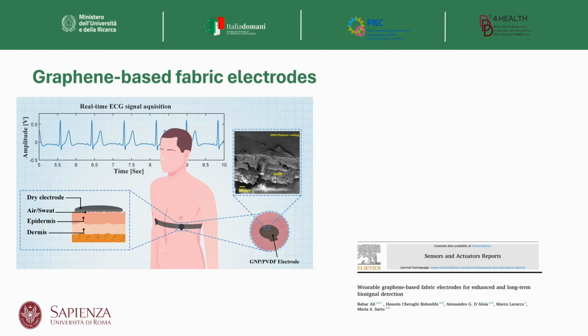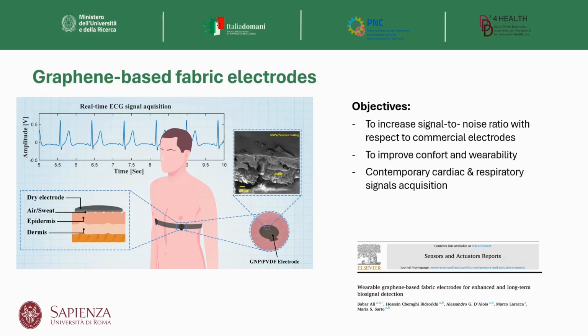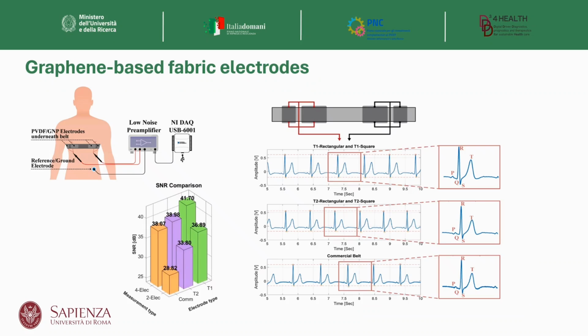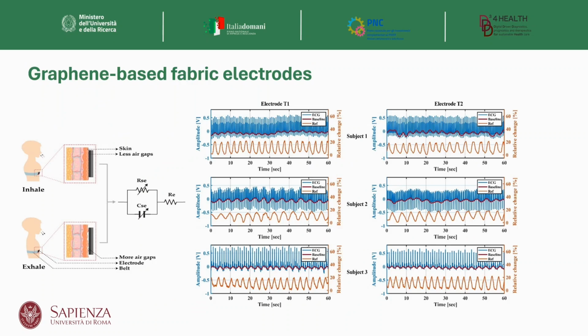Here are the electrodes we fabricate. Here the main problem is to enhance the signal to noise ratio, which is a crucial point, and at the same time to use the same electrode to measure cardiac and respiratory signals simultaneously, which with a commercial electrode you cannot do. So here you see the validation and testing of the electrodes, in which you can see there is a very high signal to noise ratio. And therefore, once we made the test here, we made the demonstration and comparison with a commercial electrode.